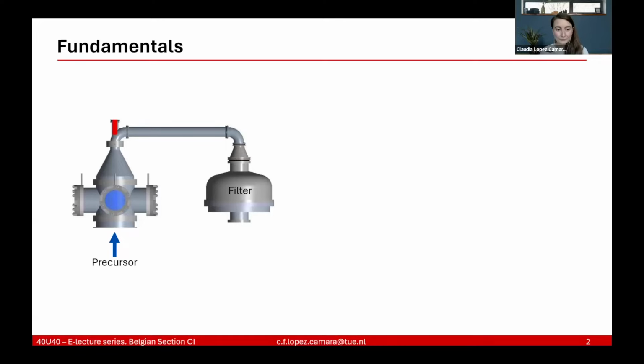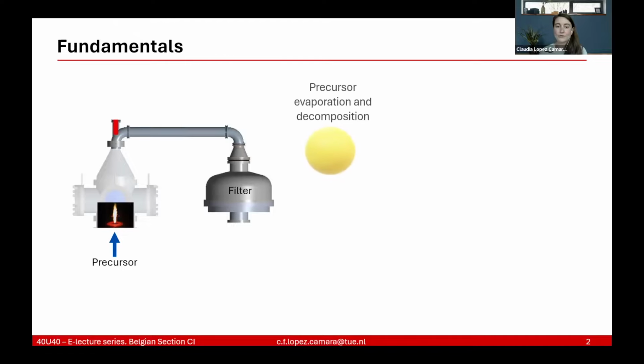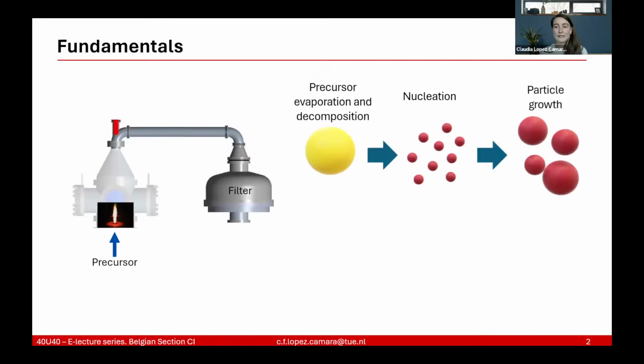When the precursor enters the reactor, the first thing it finds is a high temperature region, either a flame, a plasma, or even a hot wall reactor. Basically, it's a high temperature region. In this case, I put a flame there. When that happens, the precursor evaporates and decomposes, and then it nucleates, particle growth happens, and the particles get deposited on the filter. So this is the fundamentals of all sorts of gas phase synthesis.